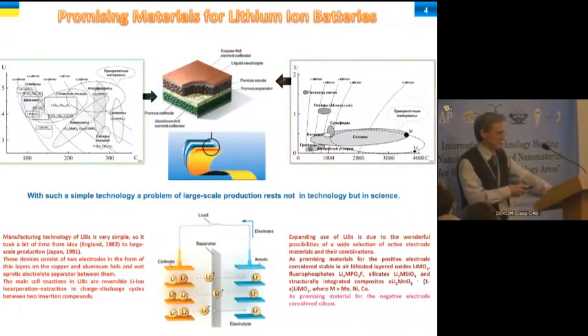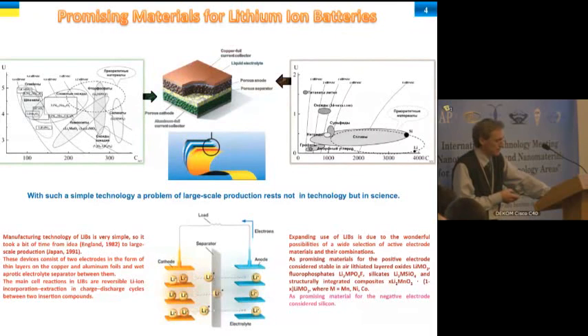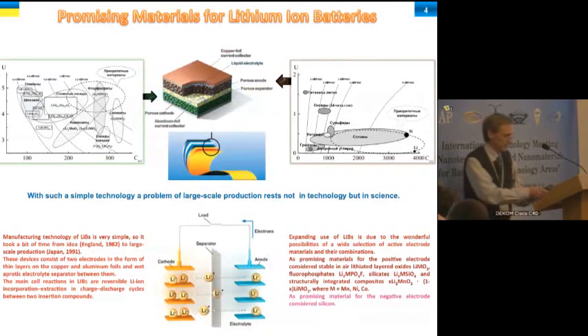As promising materials for the positive electrode are considered stable in air lithiated layered oxides, fluorophosphates, silicates, and structurally integrated composites. As promising material for the negative electrode is considered silicon. Readily available and low-cost silicon is considered as an alternative for the conventional graphite anode because of its high capacity for lithium-ion storage, nearly tenfold higher than that of graphite.